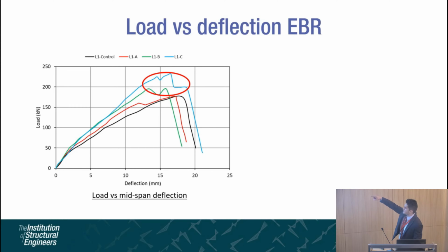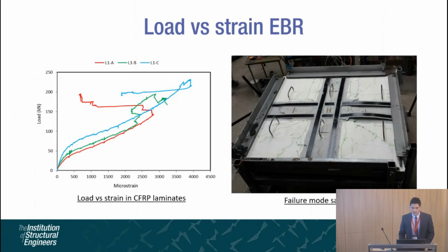As you can see, there is a drop after reaching the maximum load. It's showing failure of one of the anchorages. So by placing 2 anchorages next to each other, we are gaining additional strength. We are describing this as residual load, so it will be used as a warning sign. Once the first anchorage fails, people can vacate the building and it could be restored. The load versus strain graph is shown on the left-hand side of the slide. We didn't reach maximum capacity of the FRP. It reached up to around 25 to 30% of its rupture strain before failure.